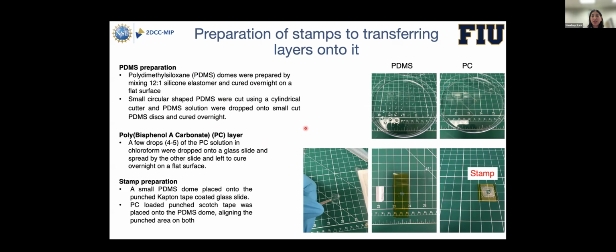We prepared it by using a PC solution in chloroform, and we used four to five drops onto one glass slide, and took another glass slide and put them together onto each other, and then slightly slid it from one end to the other, so that we have a layer of PC material on both the glass slides. Then we left them on a flat surface overnight to cure the PC layer.